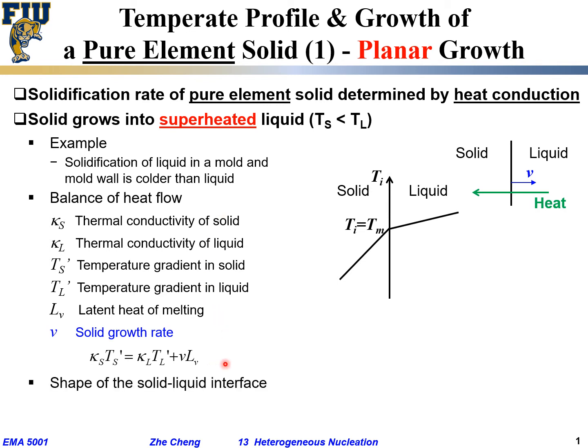With that in mind, let's consider the shape of the solid-liquid interface, or the stability of this interface. Let's say initially it's a flat interface between solid and liquid, but then at any moment we form a so-called local protrusion, a local solid protrusion into the liquid. Solid is still on the left, liquid on the right, and we have a protrusion of solid into the liquid. And again, the heat flow direction is the same, from hotter liquid on the right to colder solid on the left. The heat flow direction does not change. But let's say we have a local protrusion. Okay? When you start to consider this equation, some interesting observations occur.